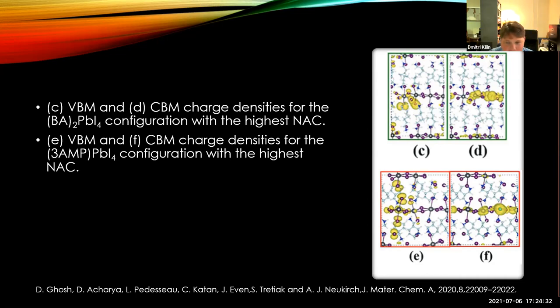David, would you like to help? Perovskites are ionic species. So the ammonium bonds with the, I think you said these were iodine models? Yep. So it'll bind with the iodine and the organic tails will form like a hydrophobic layer. That's what gives you your quasi 2D structure. So they need to balance the charge. The lead and iodine form a lattice where each lead has six iodine neighbors and forms a stable octahedral lattice. But then lead is 2 plus, iodine is 1 minus, and there is no way to form a periodic structure with zero charge. They need additional plus charges to make it neutral.